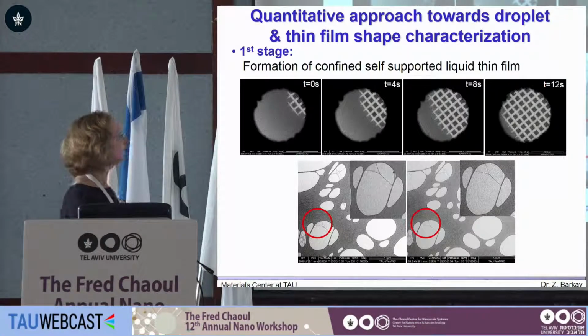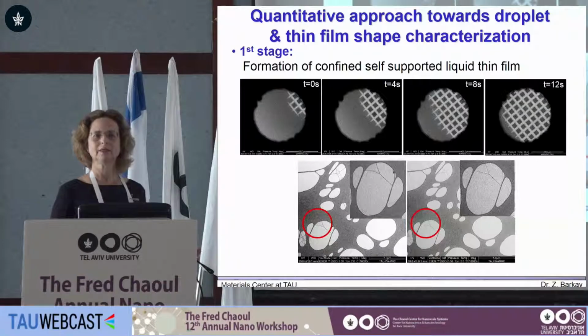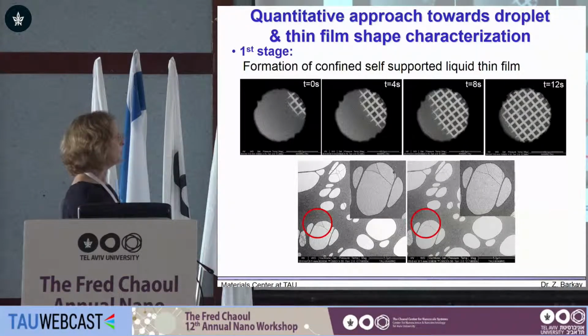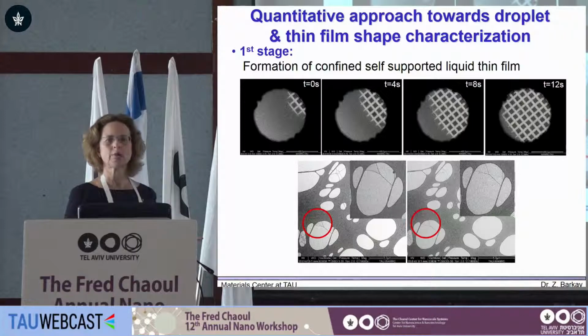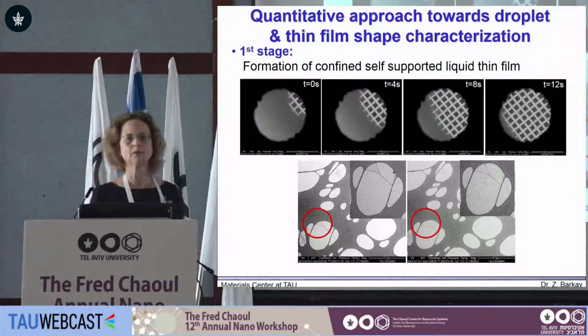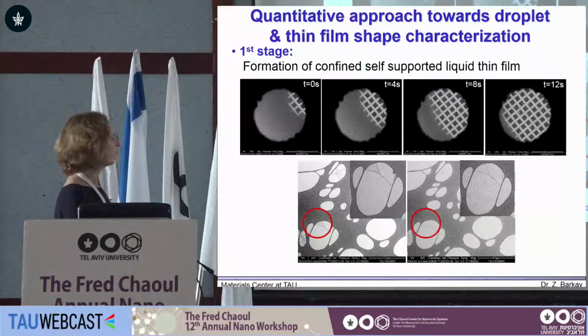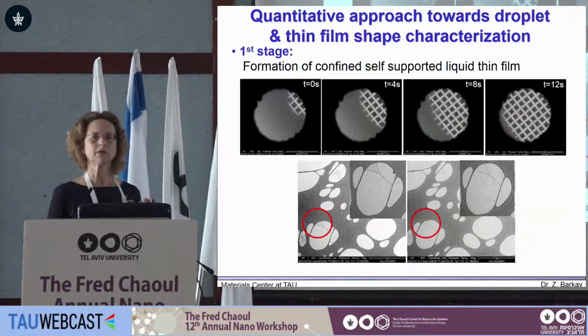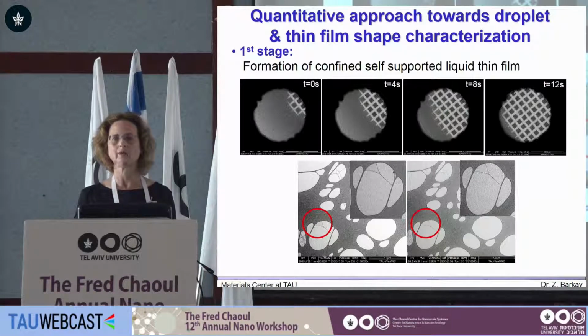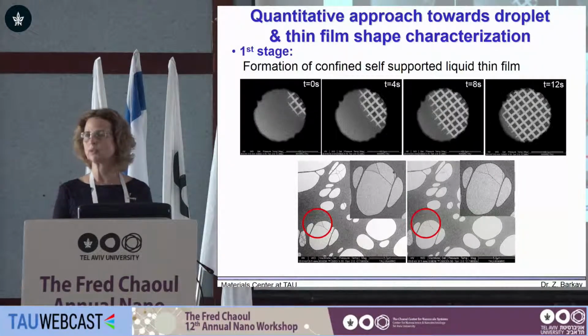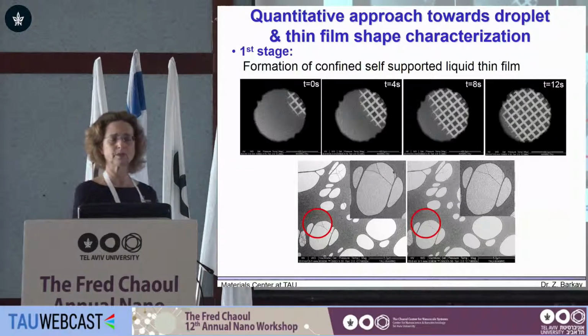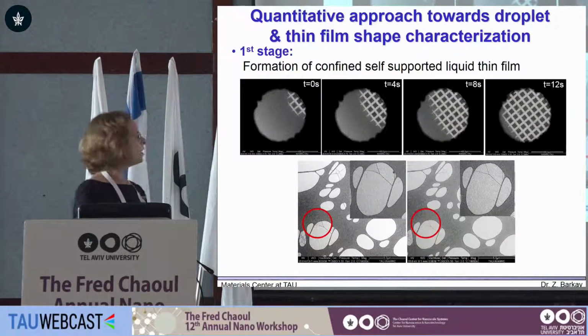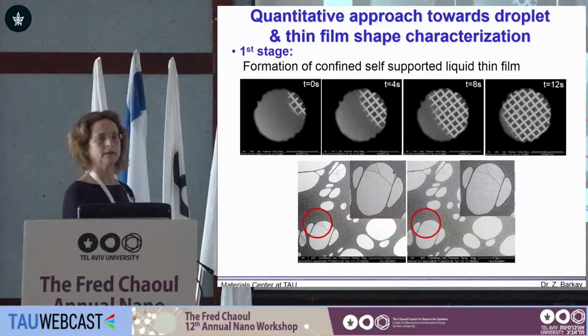Finally, we can end up with a grid which looks almost dry, but is just almost. Zooming on one of these quarters, we see the shape of this particular grid, which is a polygonal structure. If you look very precisely, you can see some contrast here different from the other regions - these are actually very thin liquid films trapped inside. To make the story short, the thickness of these liquid films is around 10 nanometers.